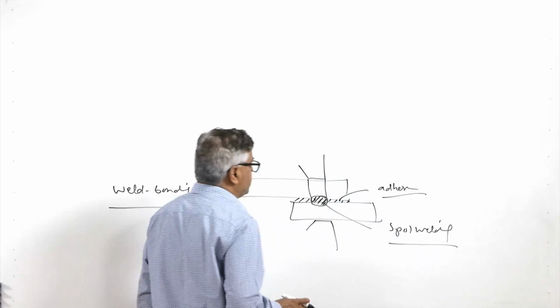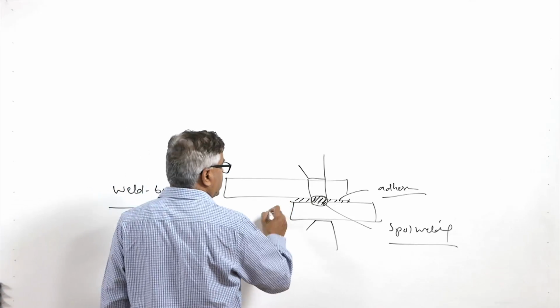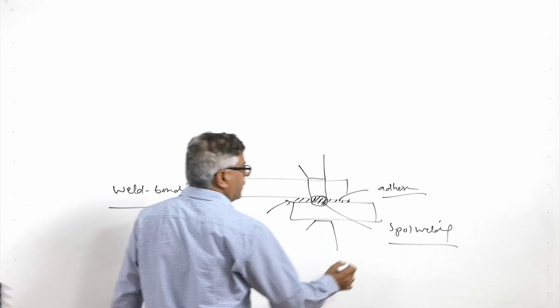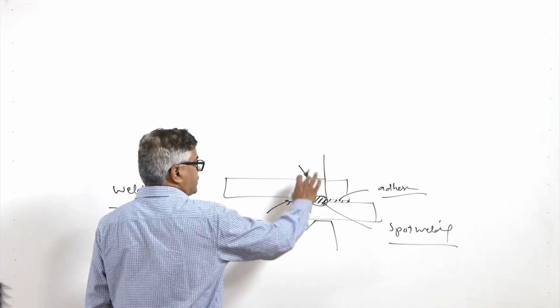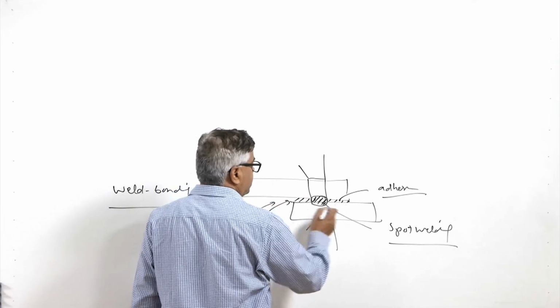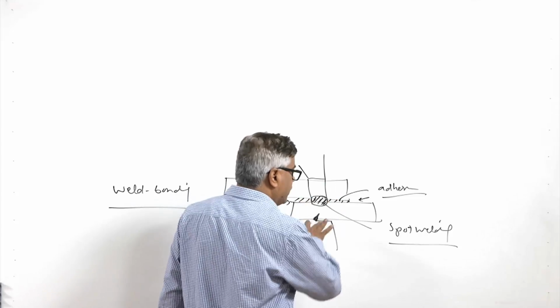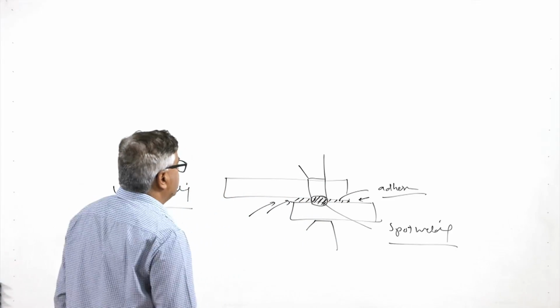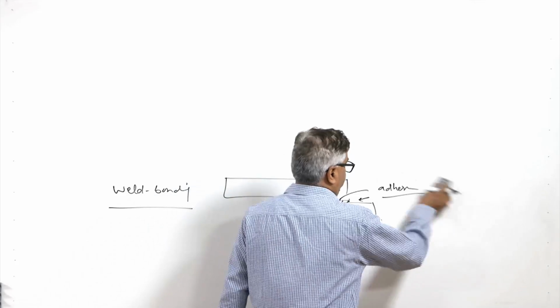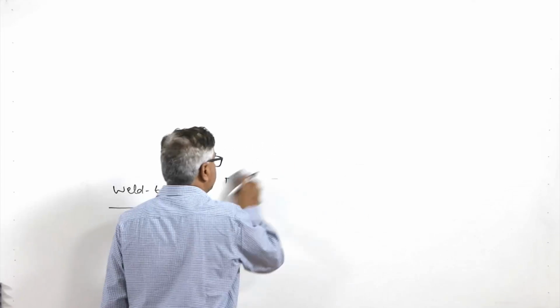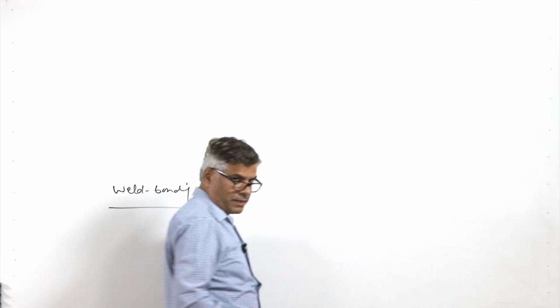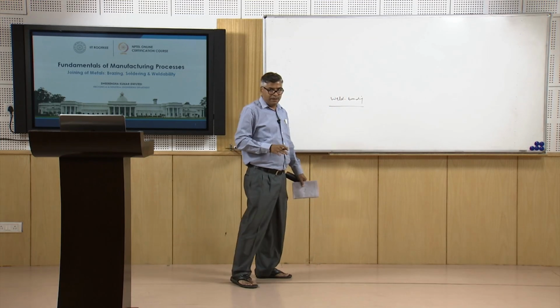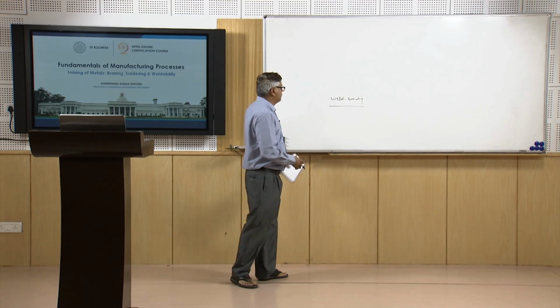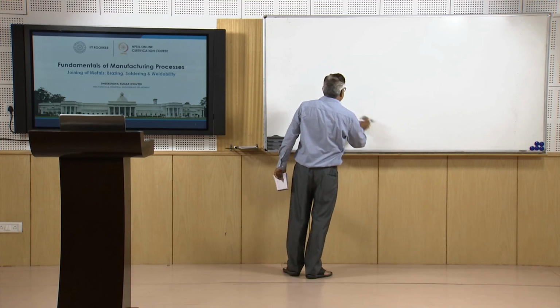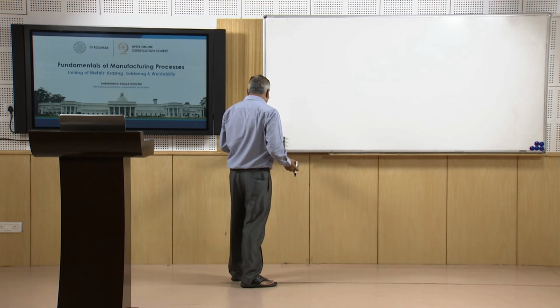So, there are two approaches which are used: in the first, adhesive is applied, then a spot weld is made, thereafter curing is done, and in the second one, first the spot weld is made, then the adhesive is allowed to flow in, and thereafter curing is carried out. This kind of joint offers very good strength, and the fatigue resistance of such joints is found to be much better than simple spot weld joints, because it distributes the stresses more uniformly across the joint area, which in turn helps in increasing the strength and the fatigue strength of the joint. Now, we will talk a little bit about the